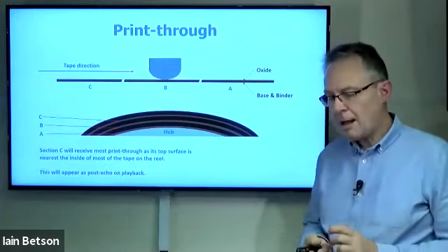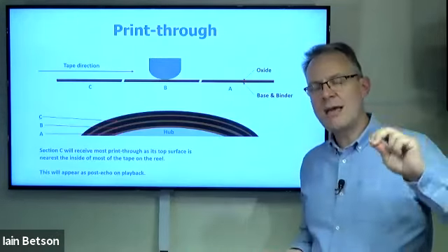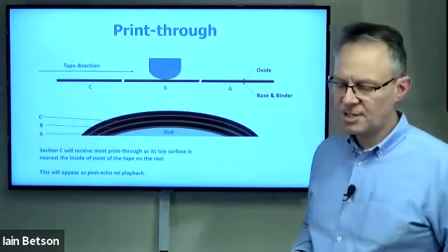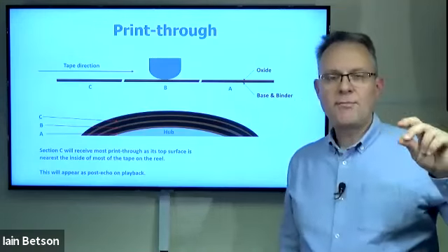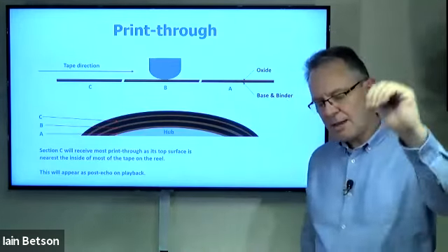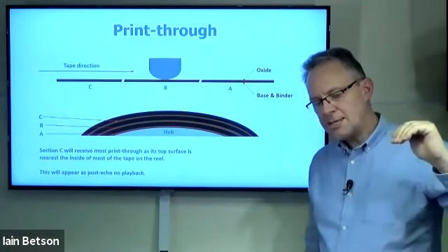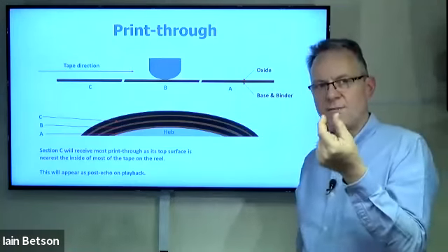However, I spoke way back about remanence and how much level you can put onto the tape. If you can't put a lot of signal onto the tape, you don't get a loud signal. The volume of the remanence you put on is dictated by the thickness of the oxide layer.